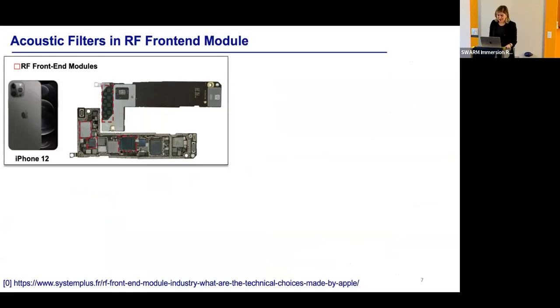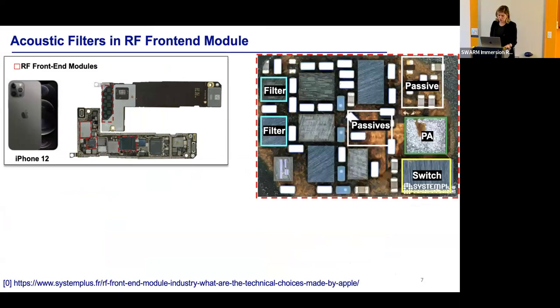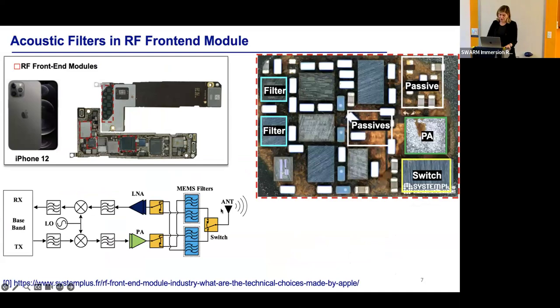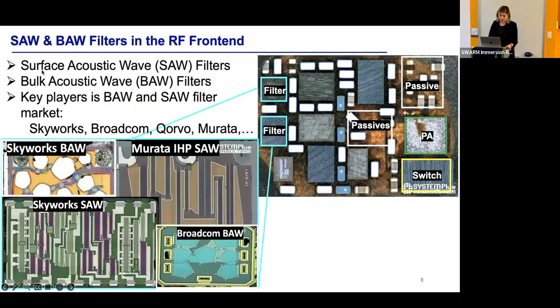All right, so having said that, let's take a look at a typical RF front-end module and see where these filters are located. Right after the antenna, it's very important to have a very low noise filter, because this is the most critical stage in terms of keeping the signal integrity and not adding noise to the signal. So here you can see these filters, and you probably have more than 40 of them right now in your cell phone that use acoustic technology. Some of the key players in industry for building these types of filters are Qorvo, Skyworks and Broadcom for BAW, and Murata and Qorvo also for SAW. So these are the key players in the bulk acoustic wave, BAW, and surface acoustic wave filters. Now, these frequencies have traditionally been limited to below 3 gigahertz.